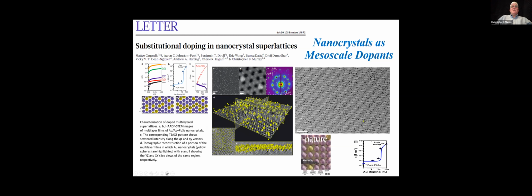In this particular example, what we're showing here is the idea that you can organize these artificial atoms into extended arrays, and then by choosing a particle of a different composition, but controlling its shape and its surface treatment so that it basically can fit optimally on the lattice sites of the majority phase, we can start to develop systems that have a combination of periodicity within the lattice, but also the introduction of new centers for electronic charge introduction or for optical properties. Happens to be plasmonic gold in this particular case.